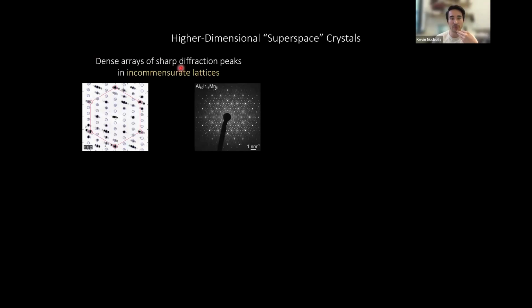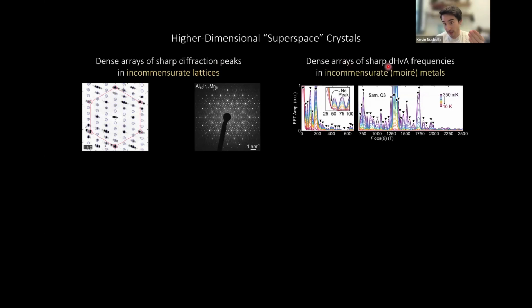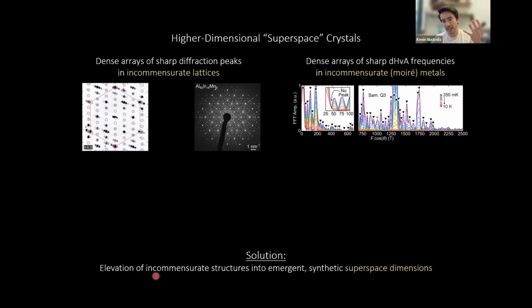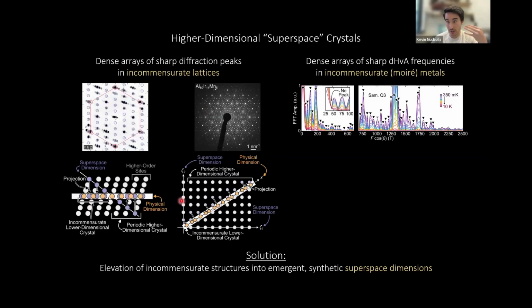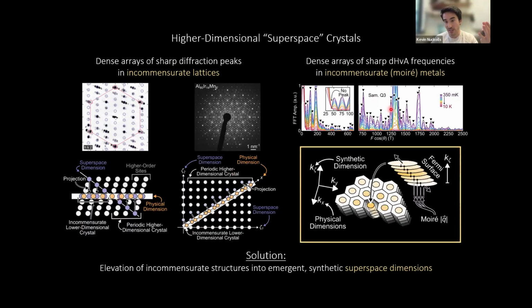So the dense arrays of sharp diffraction peaks seen in incommensurate lattices, and this dense array of sharp de Haas-van Alphen frequencies that we observe in an incommensurate Moiré metal, we believe that both of these ideas can be similarly rectified by elevating incommensurate structures into emergent synthetic superspace dimensions. In the 70s, people recognized that there are some constructions for producing superspace crystals based on lattice mismatches in real space. And we'll show that we can actually understand these quantum oscillations from a kind of momentum space analog.